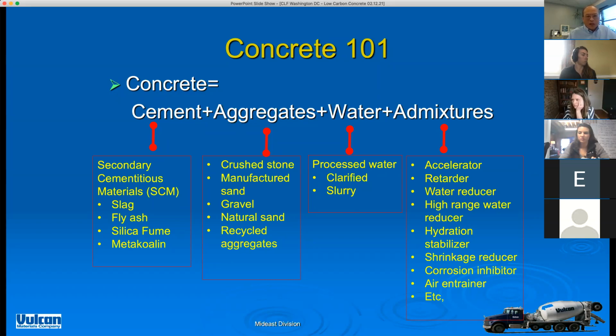And then aggregates, you can get crushed stone, manufactured sand, washed gravel, natural sand, and recycled aggregates, like taking leftover concrete that comes back to our plant from the project. People order 10 yards, they only use 7, and we get 3 yards coming back. What do we do? We can crush that concrete up, and it becomes a good recycled aggregate that can be put back in concrete.